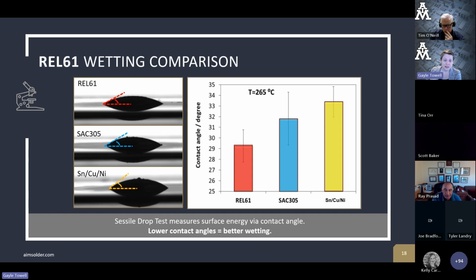Wetting comparisons. In some of our studies, we see similar types of wetting performance depending upon what we're measuring. But here we're looking at the sessile drop test, which essentially measures the angle of your drop, and a smaller angle indicates better wetting. When we compare REL61 to SAC305 to a tin copper nickel alloy, REL61 has the lower contact angle, which tends to correspond to better wetting.